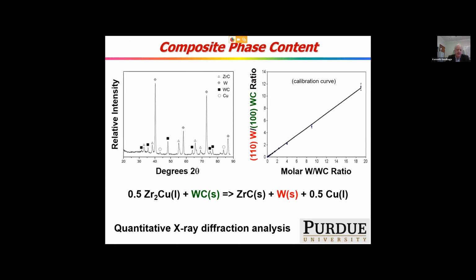We can also quantify the phase content and the relative porosity by using techniques like quantitative X-ray diffraction. On the left, you see a typical copper K alpha X-ray diffraction pattern for such a cermet. You see the two product phase peaks, ZrC and tungsten, as well as some residual tungsten carbide and some residual copper in the sample. To quantify the phase content, we can, in advance, pre-mix known amounts of Zr2Cu and tungsten carbide with the products for, say, 10% reaction, 20% reaction, 90% reaction, and pre-X-ray those known amounts to generate a calibration curve. If we compare the area under the 110 tungsten peak to the 100 tungsten carbide peak, tungsten's a product, tungsten carbide's a reactant, we can get the extent of reaction from X-ray diffraction analysis.